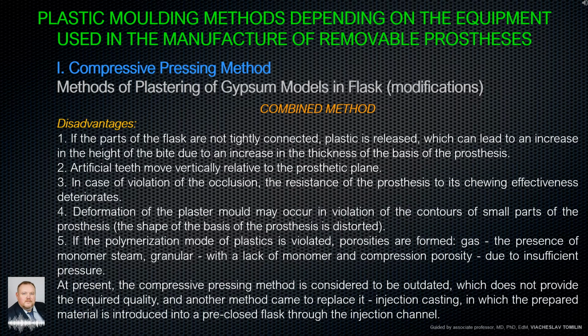Combined method. Disadvantages. 1. If the parts of the flask are not tightly connected, plastic is released, which can lead to an increase in the height of the bite due to an increase in the thickness of the basis of the prosthesis. 2. Artificial teeth move vertically relative to the prosthetic plane. 3. In case of violation of the occlusion, the resistance of the prosthesis to its chewing effectiveness deteriorates. 4. Deformation of the plaster mold may occur in violation of the contours of small parts of the prosthesis, the shape of the basis of the prosthesis is distorted. 5. If the polymerization mode of plastics is violated, porosities are formed. Gas, the presence of monomer steam, granular, with a lack of monomer, and compression porosity, due to insufficient pressure.